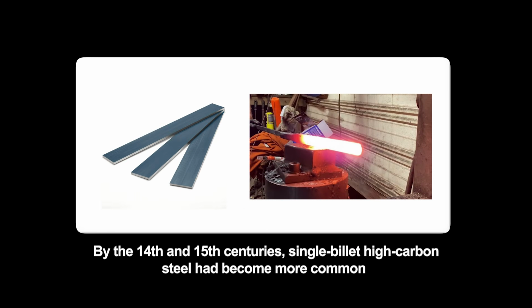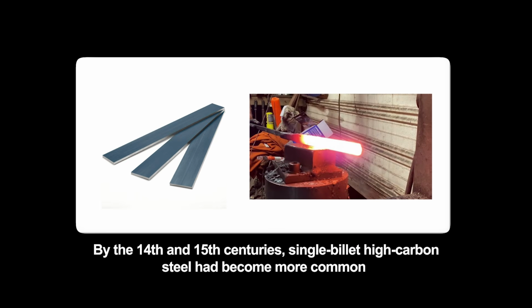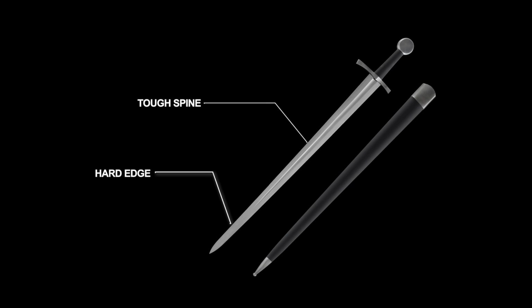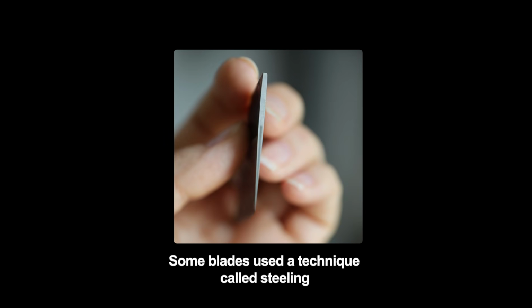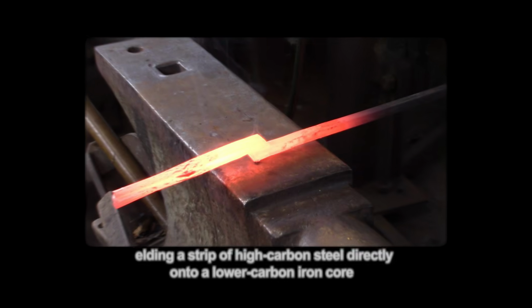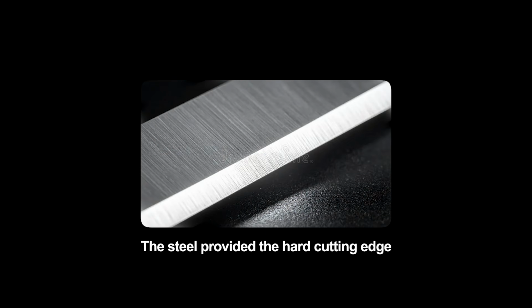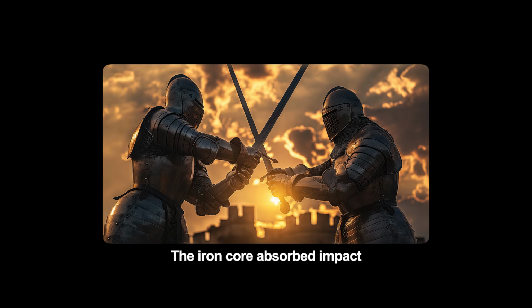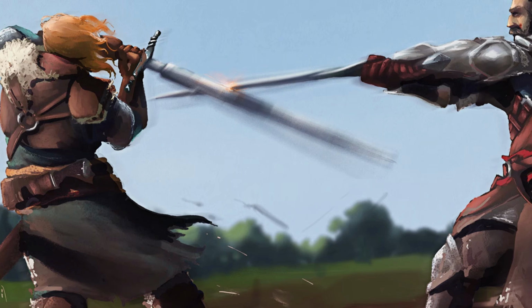By the 14th and 15th centuries, single billet high-carbon steel had become more common as steel production improved, but the principle remained. The edge needed to be hard, and the spine needed to be tough. Some blades used a technique called steeling, welding a strip of high-carbon steel directly onto a lower carbon iron core. The steel provided the hard cutting edge. The iron core absorbed impact and prevented the blade from shattering under lateral stress.